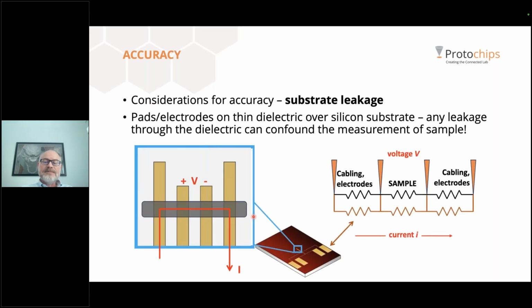One of these is substrate leakage. Now, any form of leakage in your measurement is bad. You want all the current focused on your sample and only on your sample. Any current that flows around the sample and parallel to it and can't be accounted for will result in measurement error, especially for high resistance samples. And high resistance samples are typical in the TEM because, like I said, everything is thin and small, right?